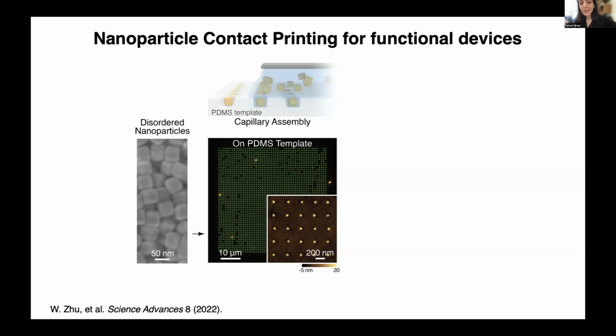This is a dark field image of spatially arranged nanoparticles. At this point, the nanoparticles are out of the solution, and the inset shows AFM characterization of the particles, and that gives you more clear information about the structure of the nanocubes and exact placement. Now, at this point, the nanoparticles are actually embedded into the template material that you've used to spatially arrange the particles.